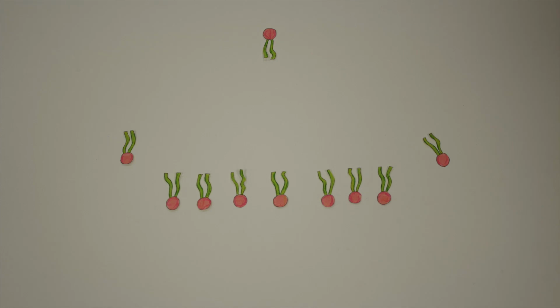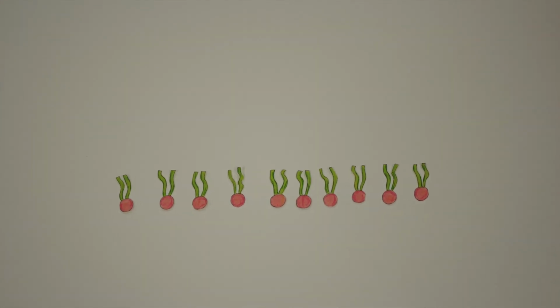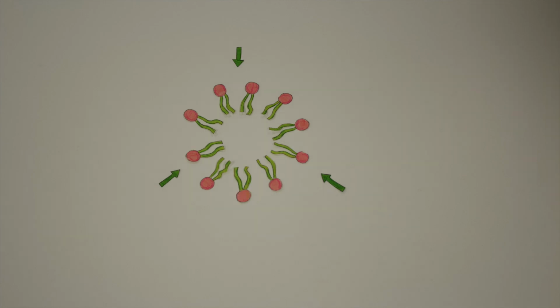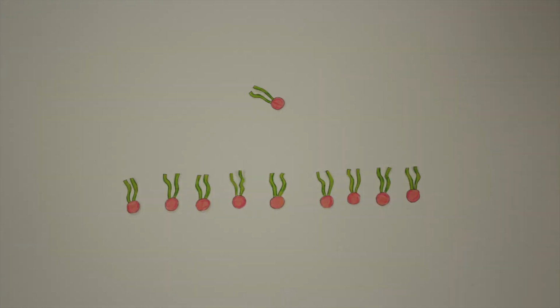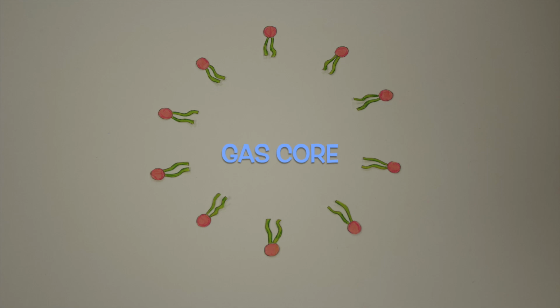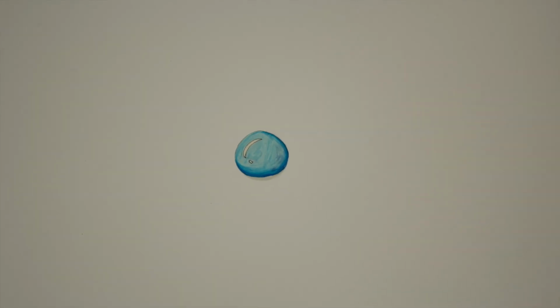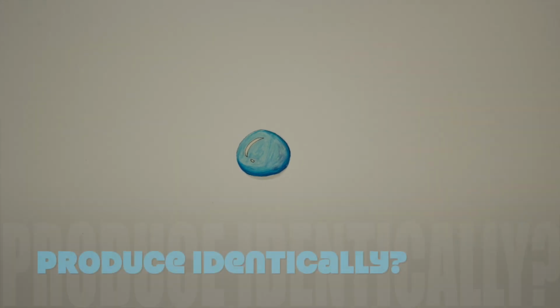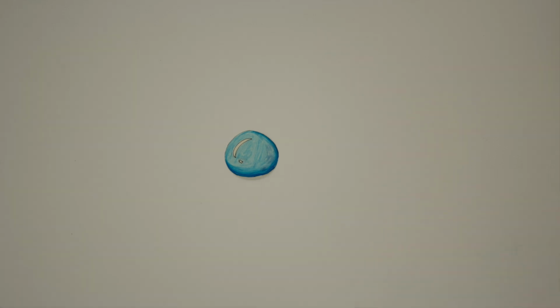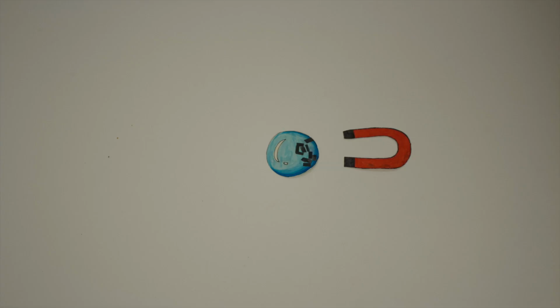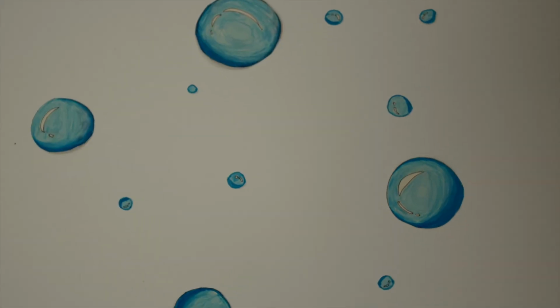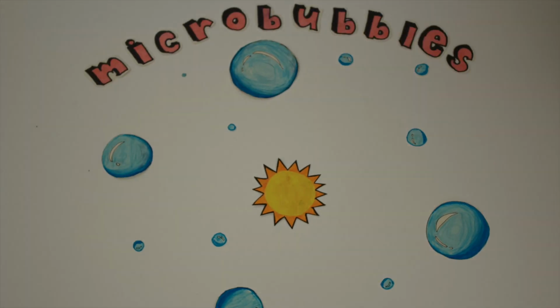The lipid molecules are held together by weak forces, without chain entanglement, meaning the shell can expand and compress its area. They are also able to reseal around the gas core following fragmentation. Despite all their benefits, microbubbles still need to be improved. Microbubbles are currently very difficult to produce identically, manipulate, and predict. One way to counteract this is to place magnetic nanoparticles inside the microbubbles and apply an external magnet, thus directing them around the body. With the development of microbubbles, the future of clinical care looks bright and bubbly!